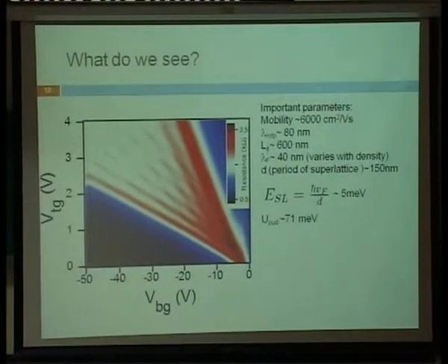So just a quick idea about the relevant parameters for the device. These are, in the days of boron nitride and suspended graphene, relatively low mobility, but they have interesting physics. So the mean free path is roughly about 80 to 100 nanometers. So we are not quite in the ballistic limit; we are in the diffusive regime. We have about 50. I think Sudipta can tell you 40 to 50 or 30, depending on the device.